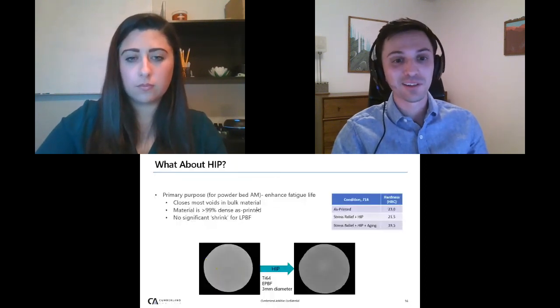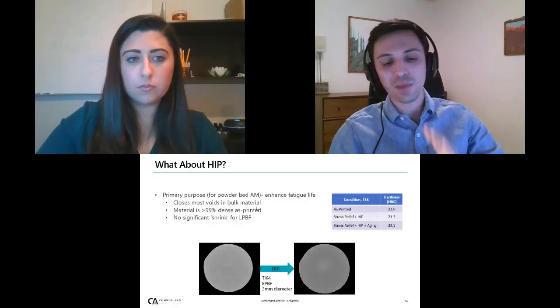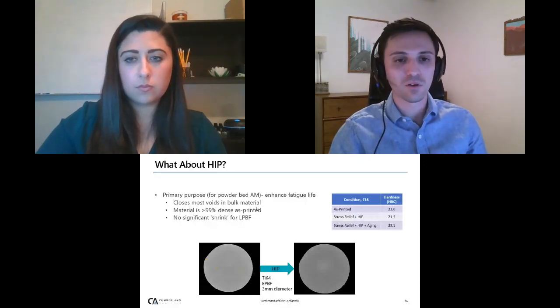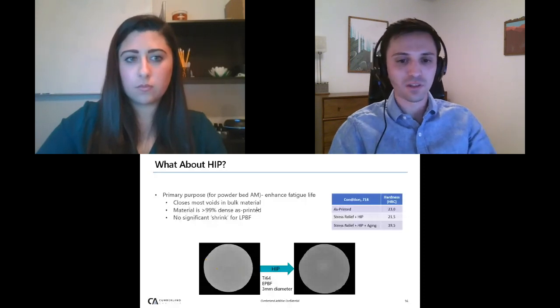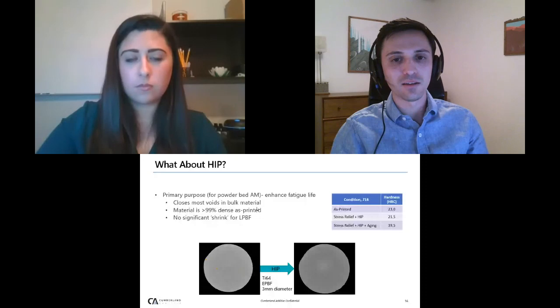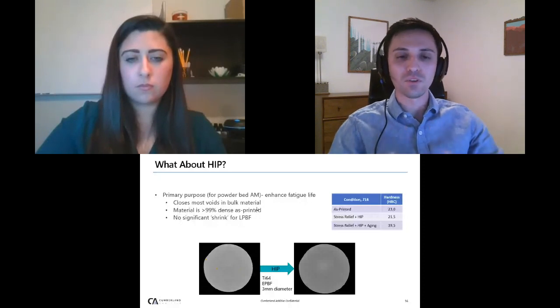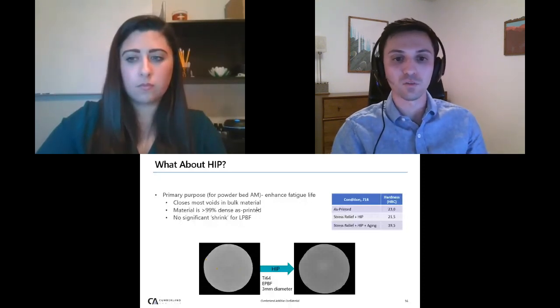Okay, what about HIP? So in powder bed fusion, you're getting a part that's greater than 99% dense right out of the machine in a well-controlled process. But even then, there's going to be some little teeny tiny voids, and running HIP can enhance fatigue life. So really the purpose with powder bed fusion and HIP is to enhance fatigue life. There's no significant shrink that happens through this process because the amount of density that's healed is low. So it's just something to think about. We're not looking at a sponge that then gets shrunk down by HIP.